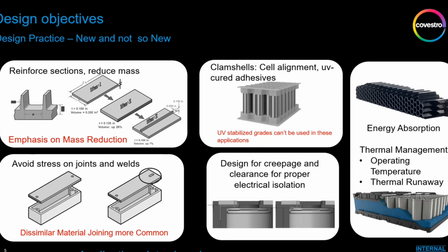So with smart design in batteries, you can get those higher energy densities and still achieve the performance requirements that you need. Another thing that's fairly common with battery applications is many people who are doing clamshells for cylindrical type cells, they will tend to use UV cured adhesives to be able to mount the cells into the holders and keep them locked in place for the assembly operations. For example, wire bonding, which is critical, obviously, to the battery's performance. You need to have the cells held rigidly and consistently in the same location for the wire bonding equipment to work properly. So many people will use UV cured adhesives to hold those cells in place. And with a lot of materials, if it's an opaque material, you can't utilize those because you can't shine a light through the opaque materials and cure the adhesives. So we have grades. We have clear polycarbonate grades, flame retardant polycarbonates, and we have a Bayblend FR3040 EV, which all have enough UV transmission to enable UV cured adhesives to be cured through those materials.